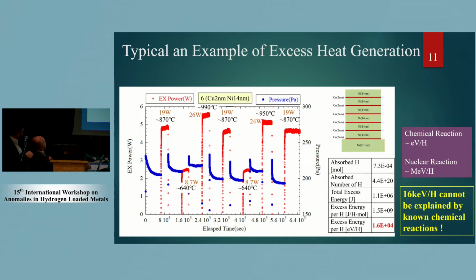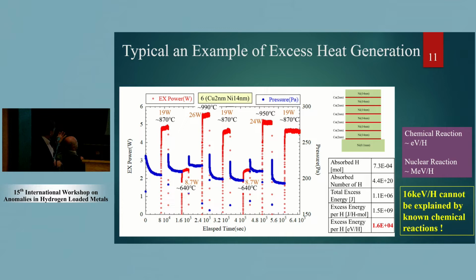Using this method, we repeat this kind of experiment to check the reproducibility. In this case, if we input 19 watt, we got almost similar excess heat. And if we decrease the input power, we also get smaller excess power. Based on this data, we can calculate the total absorbed number of hydrogen atoms. If we integrate this excess power by time, we get total excess energy, 1.1 megajoule. So we can estimate the excess energy per hydrogen. It is 16 keV per hydrogen.